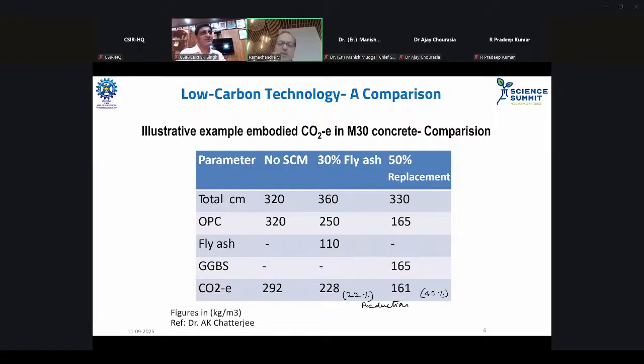That means a 22% reduction. And if we replace it 50%, either by fly ash or by GGBS and fly ash combination, as in the case of composite cement, it would reduce to somewhere around 160, which means there is a reduction of 45% carbon dioxide emission in the M30 concrete.